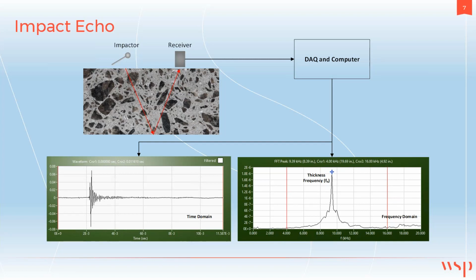So you see in the bottom left a typical impact echo signal that starts out with very high amplitude and then dampens rather quickly. Within that signal, there are vibrations at various frequencies that overlap.